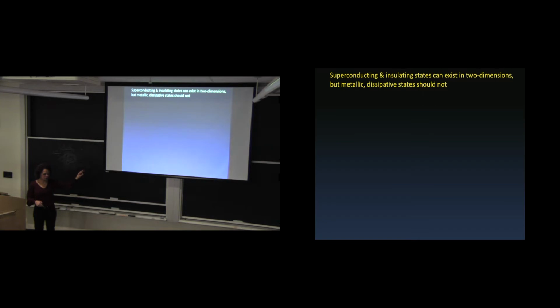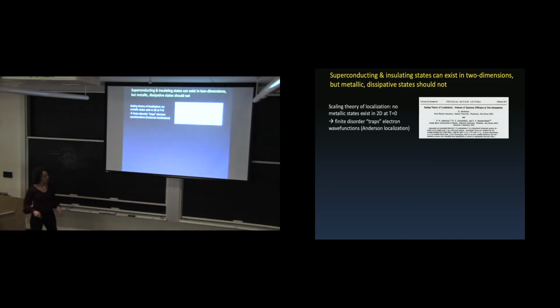in 2D, you can have this kind of quasi-long-range superconducting state, and you can have an insulating state, but you can't theoretically have a metallic state as you approach zero temperature. So 2 dimensions is even more complicated. This is the famous scaling theory of localization, which says basically, if you have a 2-dimensional metal, as you lower the temperature, any tiny amount of disorder will trap the wave functions and keep them localized. And so you end up in a localized state rather than a state where electrons can flow. So in theory, as you approach zero temperature, you should have a localized or insulating state in a 2D system. You should not approach a metallic state in 2D.